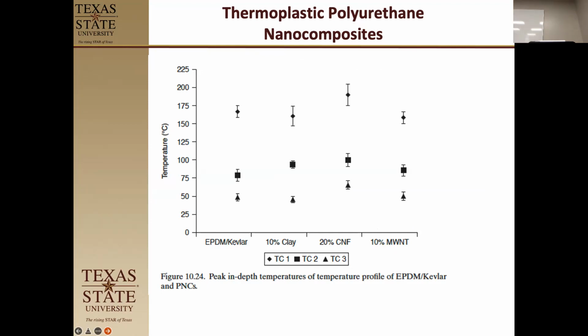We're looking at heat in-depth temperature. So one of the things your ablative material does, besides erode away, is it also insulates. And so they did a measurement of 3 different places inside of the material. They took a material and put one near the surface, one I think 5 millimeters down, one 5 more millimeters down. Okay. And then they ablated from the top and measured the temperature differential between them. So you have these right here, and they started at something like 25 degrees.